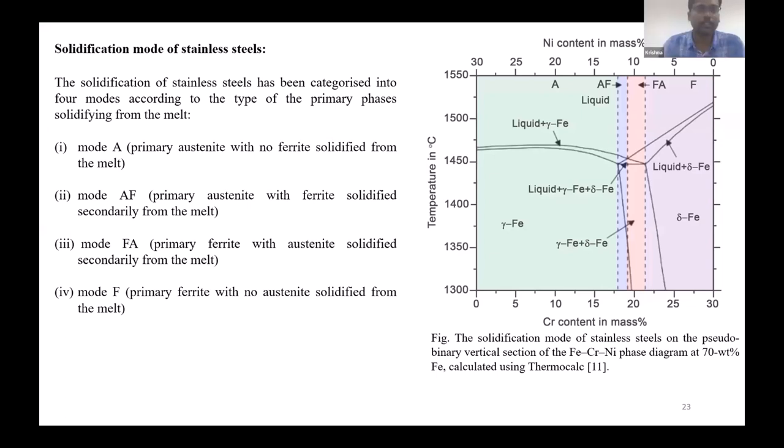So in particular for the stainless steels, we can see primarily four modes. Mode A, where primary austenite with no ferrite solidifies from the melt. Mode AF, where the primary austenite with ferrite solidifies, with secondary phases from the melt taking place, and mode FA, and mode F. So these are some different modes where different phases will be formed based on the cooling rates during the